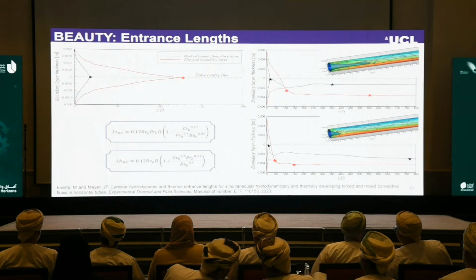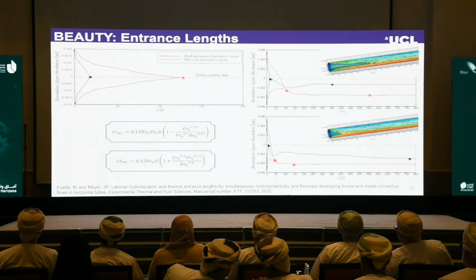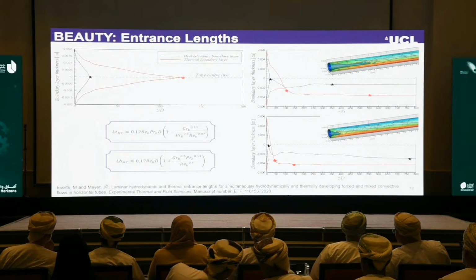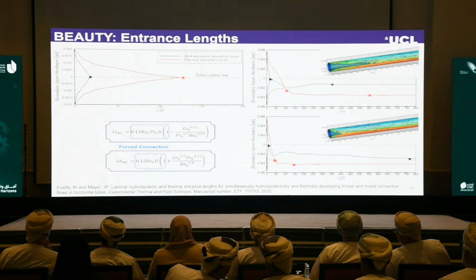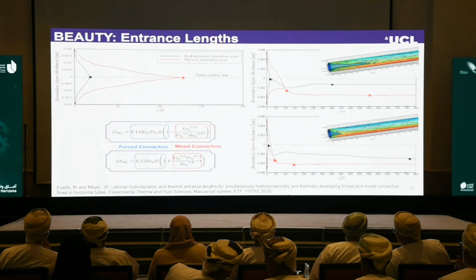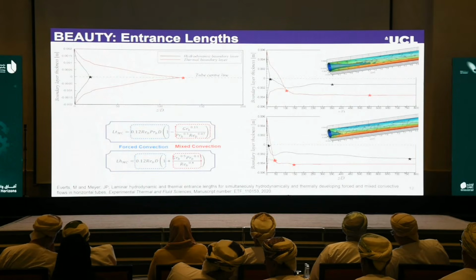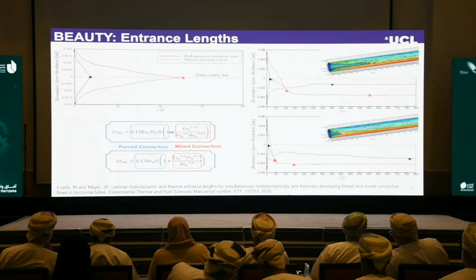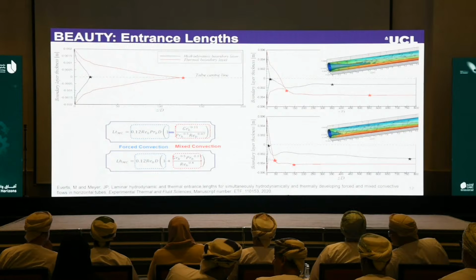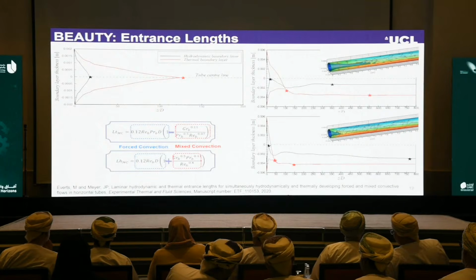So based on this, I developed two correlations that can better predict the hydrodynamic and thermal entrance lengths. And I developed it in such a way that the first part basically represents forced convective conditions, and the second part accounts for mixed convective behavior. For the thermal entrance length, there's a minus sign because mixed convective effects actually decreased the thermal entrance length, while it disturbed the hydrodynamic development, and therefore it extends the hydrodynamic boundary layer.